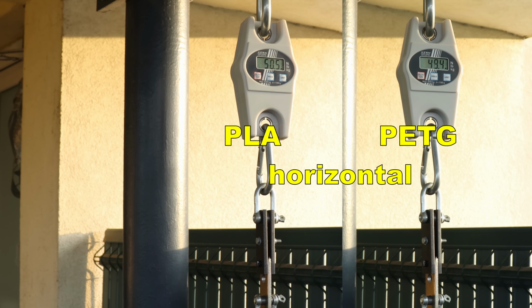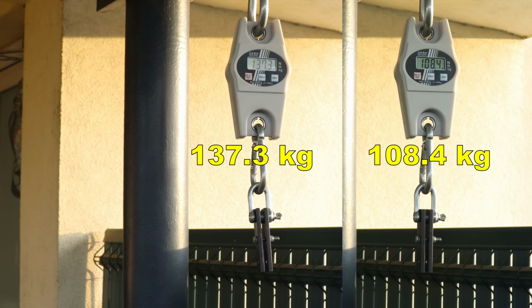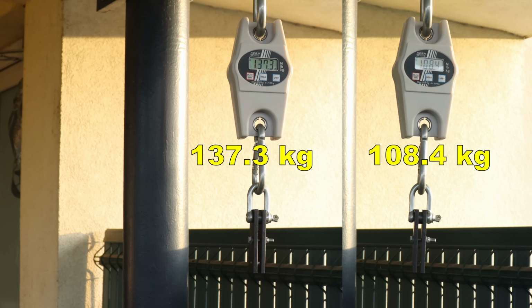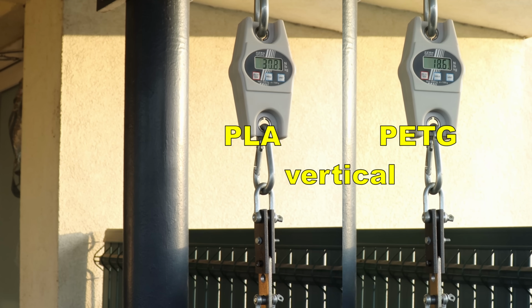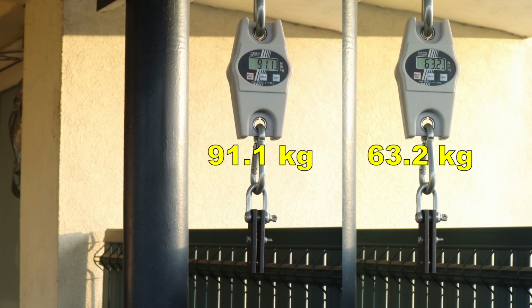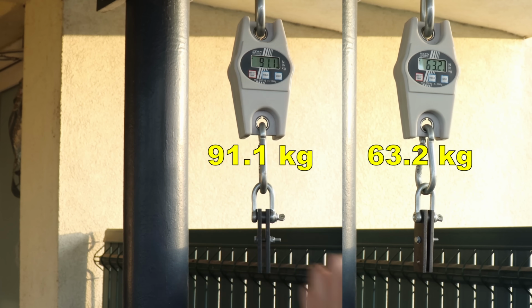Shear test, objects printed in horizontal position. Printed vertically, where the layer adhesion is important. Horizontally printed are more or less similar to the non-reinforced versions. Vertically printed objects, only graphene-reinforced PLA looks stronger, others are very similar, but here I have quite big inaccuracy because I started this testing later and I have only 5 or 6 objects in this average value.